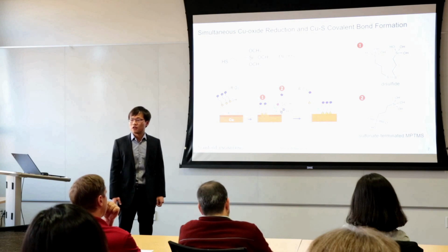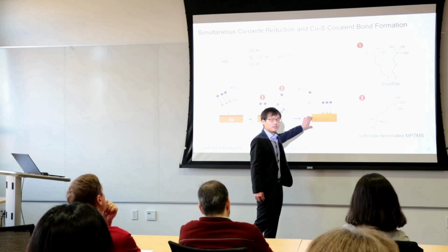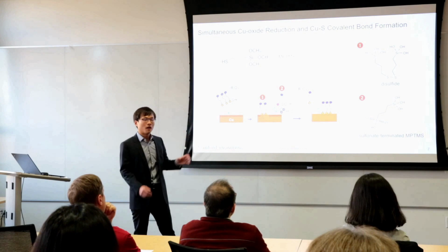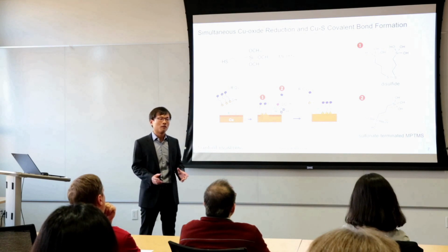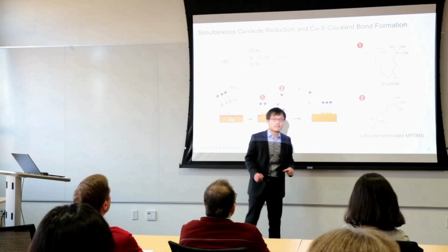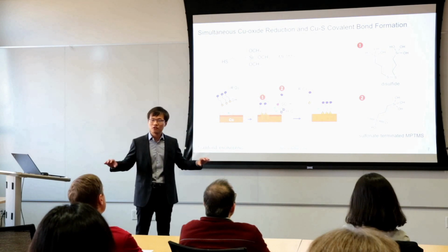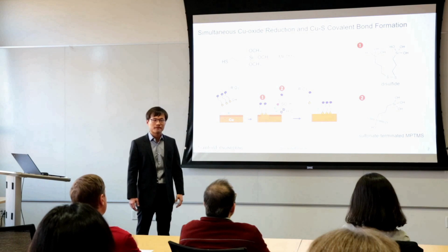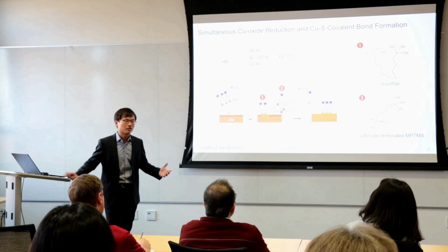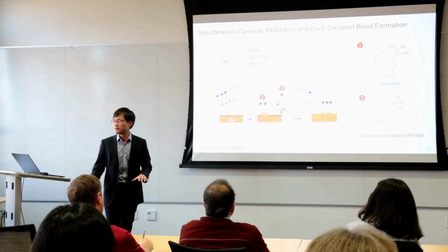In terms of formation of the strong copper-sulfur bond, when the organosilane molecule comes into contact with a newly exposed clean copper surface, either the sulfur from unreacted organosilane or sulfur from disulfide can react with the thiol onto the clean surface. And this will result in a monolayer of organosilane on the clean copper surface with the methoxy groups pointing outward. So that's how the chemistry works. Basically, the thiol functional group can not only reduce the copper oxide, but also form strong bonding with the underlying copper.